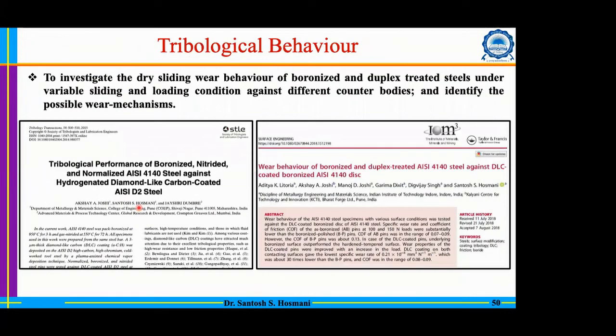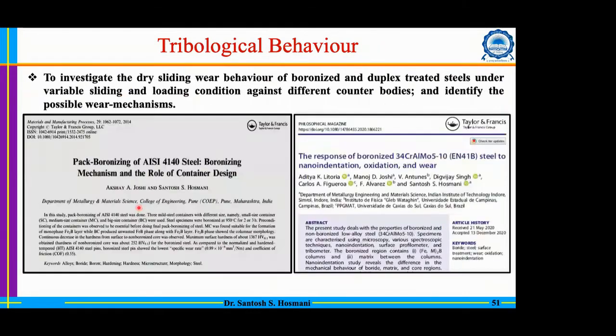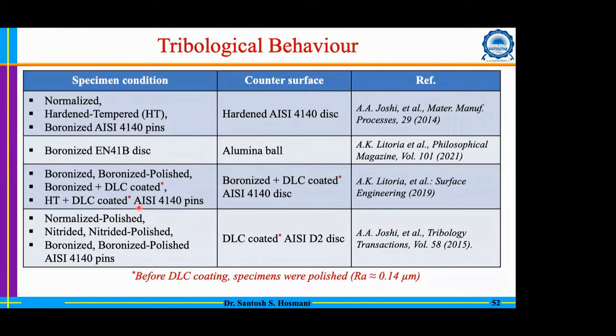So now the tribological behavior. We did an extensive study, and we compared the boronized surface with the normalized, as well as the hardened and tempered, as well as the nitrided. And then we also did a subsequent coating. Our counter surface was different. Initially, we used a hardened AISI 4140 disc, as well as an alumina ball, as well as a DLC coated one. That means we studied a wide range of combinations to prove how boronizing will be useful.